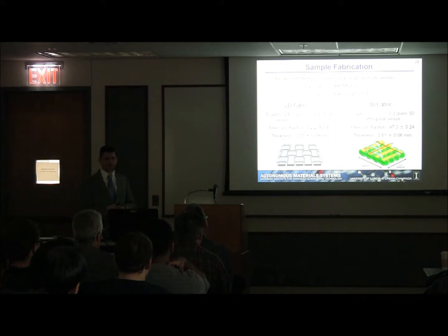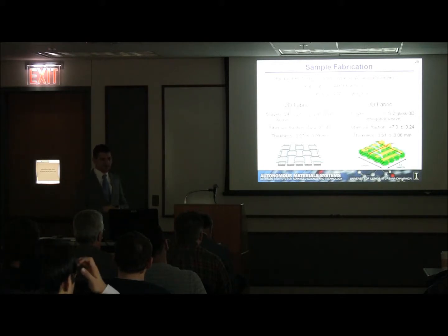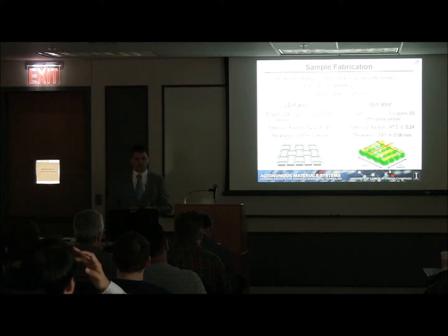To fabricate the samples, we're using the same epoxy matrix for both 2D and 3D architectures. We have a diglycidyl ether of bisphenol F resin and an aromatic amine hardener, the EPON 862 Epicure W system. We're fabricating these using a vacuum-assisted resin transfer molding technique, or VARTM, at 70 degrees Celsius in an oven. We cure these samples for 8 hours at 121 C to solidify them.